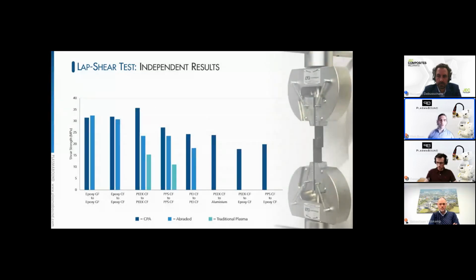In the PEEK to epoxy, or PPS to epoxy, which are the last two on this slide, this is quite interesting. There's actually no adhesive here, and this is the reason why we're interested in welding and other areas of joining and bonding. So the PEEK and the PPS CF, or carbon fiber, were the components treated in this. The epoxy CF is then cured onto the prepared PEEK and PPS material afterwards.